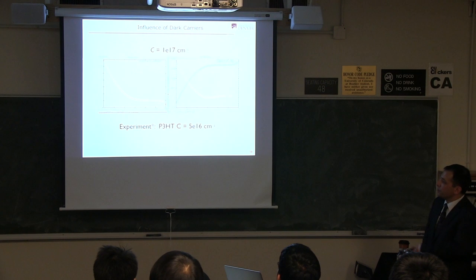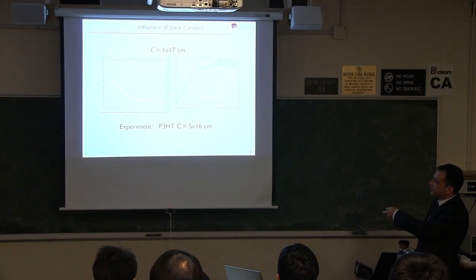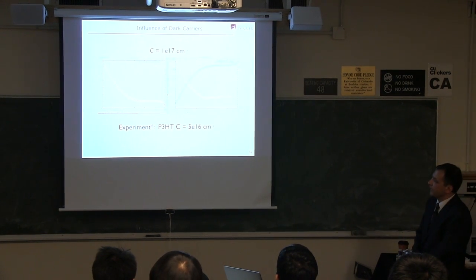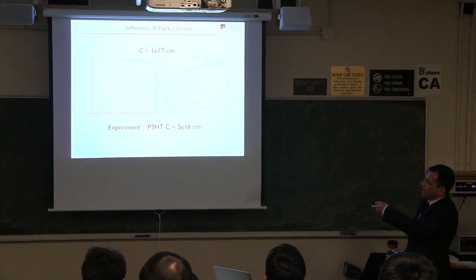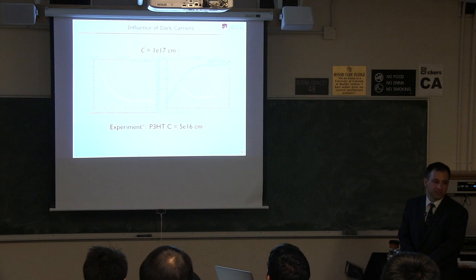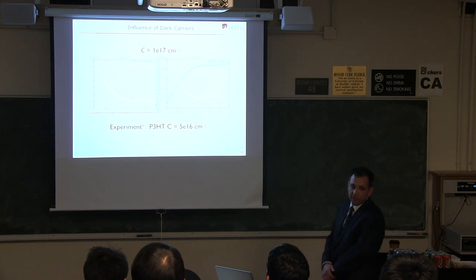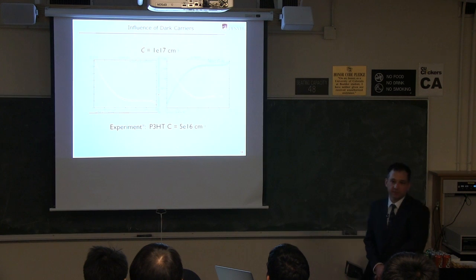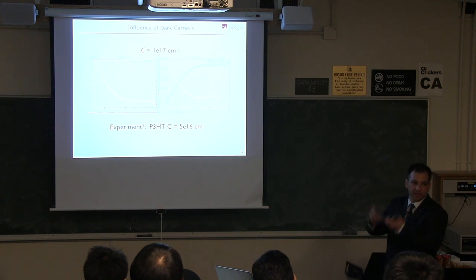The issue is that this really happens. In these materials, we measure carrier concentrations at about 10^16, and that's a significant amount that could bend the band and result in a field-free regime where you get lots of recombination in the device. So this is something we need to avoid. One way we do it is by thermally annealing the device. That tends to drive off impurities that are at least gaseous, like oxygen that is bound. We can release that. But there are other techniques we might consider as well.